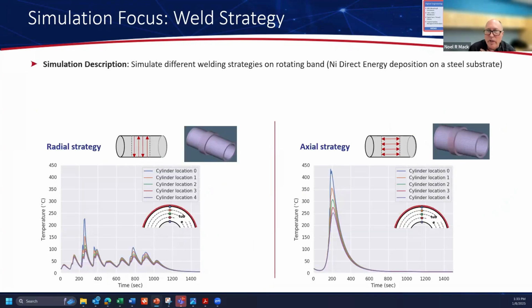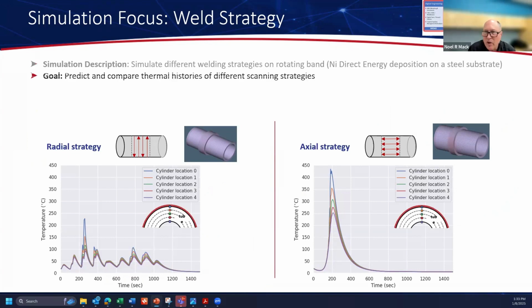So the second focus is on weld strategy. Here we're looking at simulating different weld strategies. Clearly you can weld these bands by going round and round, or you can weld them in a zigzag stitch pattern. And the objective here is to predict and compare thermal histories of the respective weld strategies, not just the thermal history of the bead we're laying down, but also the substrate, to ensure that we understand whether there's any propensity to crack through the heating and cooling cycles.